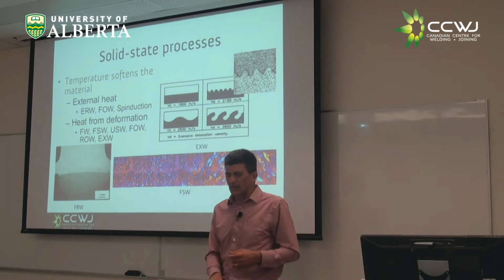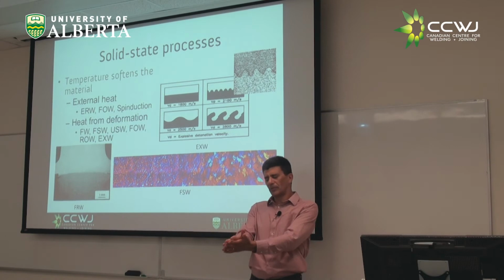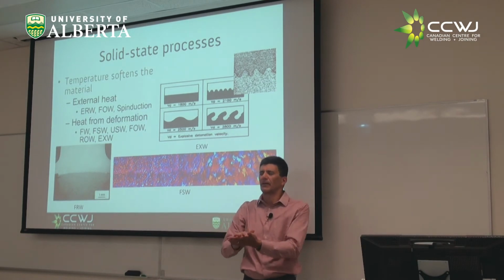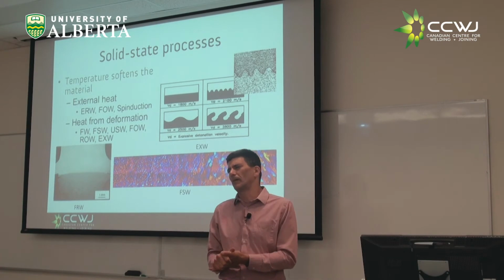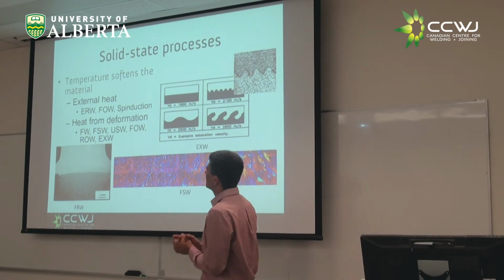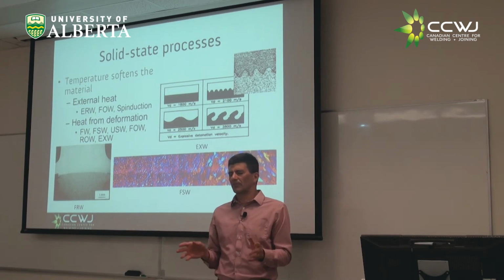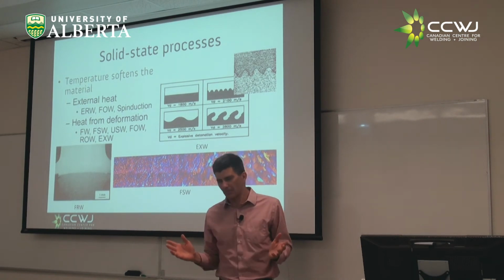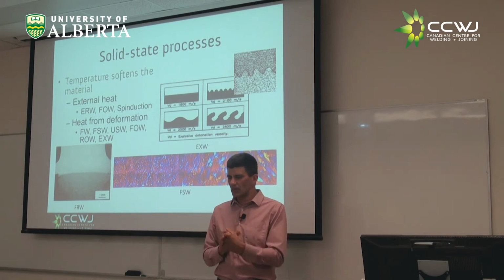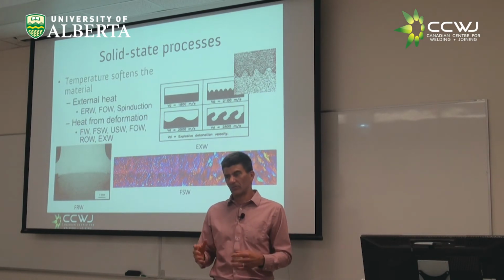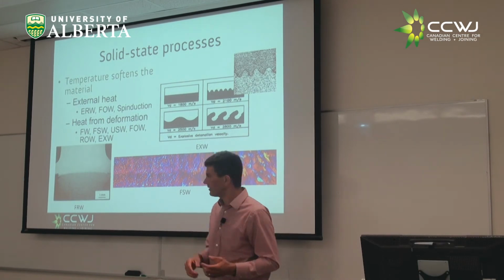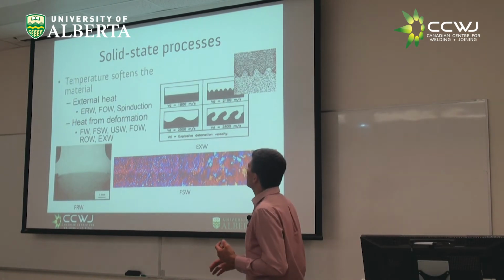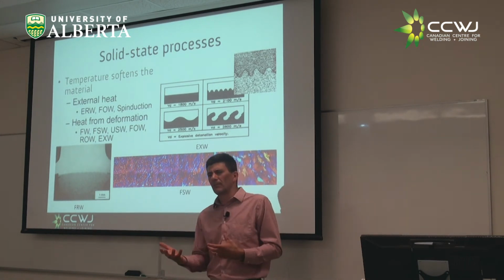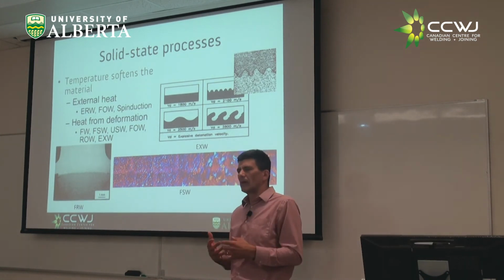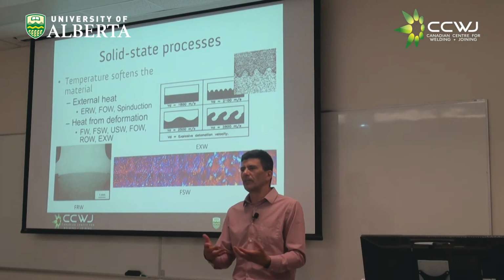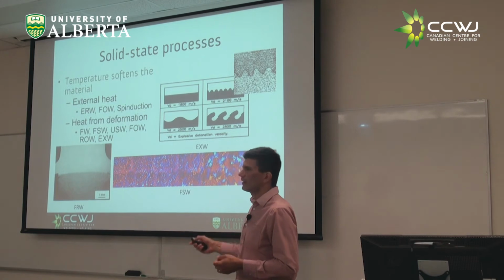So how do the atoms come in? With diffusion bonding, you just let them be, and good things happen. But maybe you want to be a little bit more intense than that, and we have those that are called solid state processes. In this case, the atoms come together because you're smashing them with a hammer, for example. You're putting so much pressure, so much deformation. The atoms come together because you're forcing them to come together, right? So often the role of temperature is to soften the material. The temperature can come from external heat sources, like you heat it up, for example, forge welding, right?